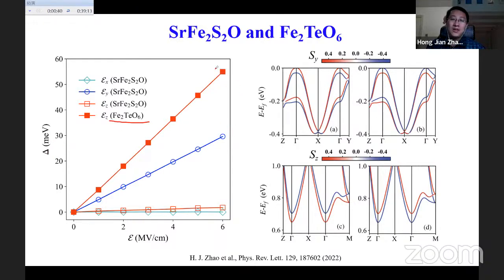So typically, creating such a sizable Zeeman spin splitting in non-magnetic material, for example in wide band gap semiconductors, would require roughly a magnetic field of about 400 tesla. So it means the trade-off between electric field and magnetic field seems good. We also found that, so here you have an electric field pointing, for example, along this direction,